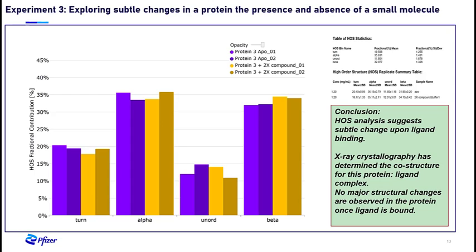For this experiment, here is the finale. I give you the higher order structure bar graph calculated from the Gaussian fit plot. Here we look at the alpha helical content, and we see there's really no overall change. The most change is observed for the beta sheet content, where we see an increase in the ligand-bound samples. This data was not a big surprise. The crystal structure for this protein bound to the ligand has been solved, and it did not show any major structural changes or movement when compared to the apo structure. The AQS3 did a nice job here.